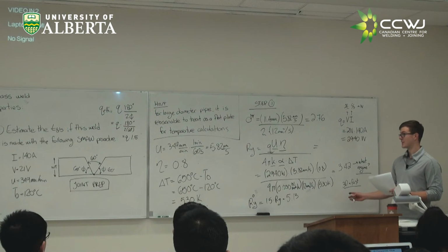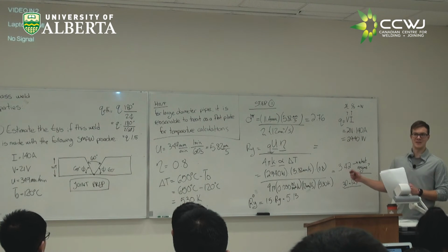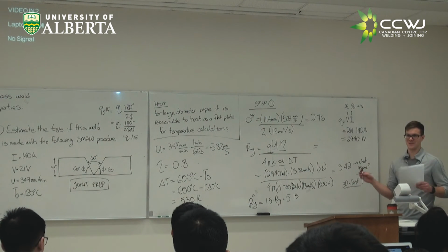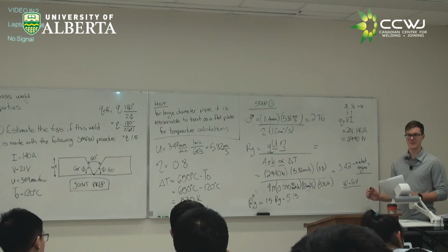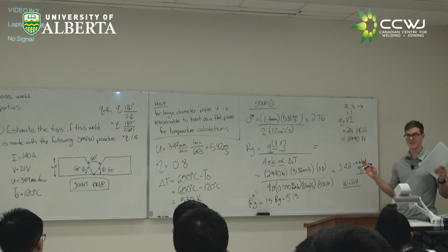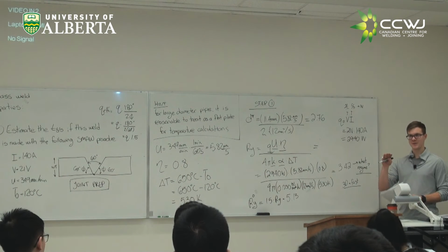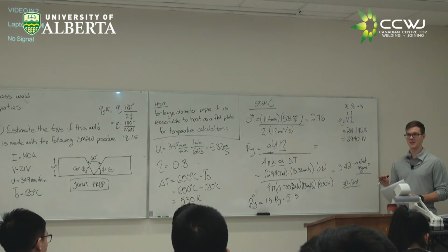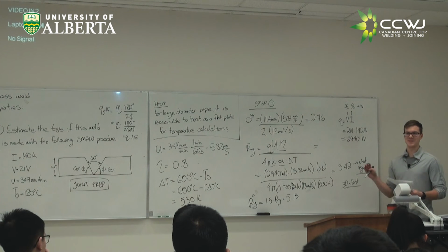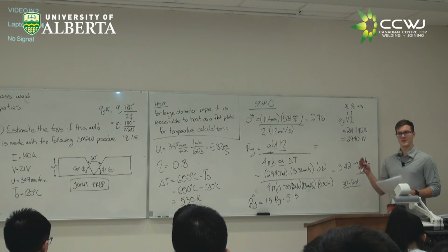These were the parameters. On the exam, we're not going to give you something that's right on the edge where you have to go back and forth and make that decision. But in practice, you saw today, a lot of those procedures from the Lincoln Handbook fall right on that boundary. So it's not uncommon to get these results where you have to make a choice. Are you going to be fast and thick or fast and thin?